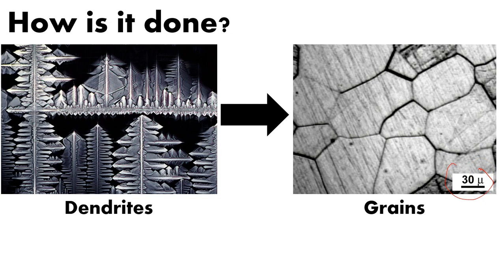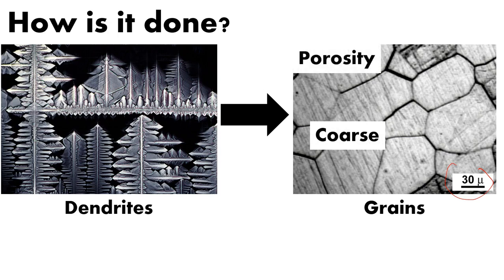Even though this is blown up a lot, you can see that these are relatively large. They're irregularly shaped. They don't have a really consistent size, and there's a whole lot of issues with the boundaries that show up and aren't necessarily consistent. So what you have is very large coarse grains, and there's a lot of internal porosity. These are internal porosity within the steel itself. And these porosities and these large irregular shaped grains have consequences.